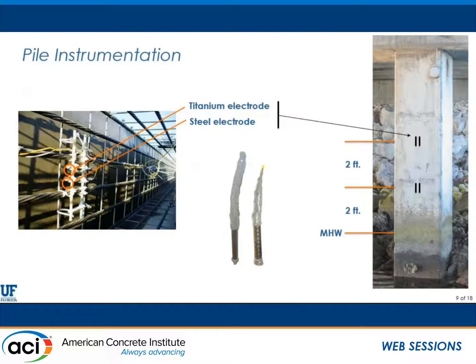So our instrumentation, this is where we really spent a lot of time thinking about what we wanted to have in place way down the road. We created electrical connections with the pre-stressing steel, so we brazed electrical connections up at the top so that we could do potential measurements straight up on the surface of the concrete, half-cell measurements with copper sulfate electrode. We also installed isolated steel and titanium pieces that look like this using a super special process that the DOT helped us with, the corrosion lab uses typically for their cathodic protection systems.